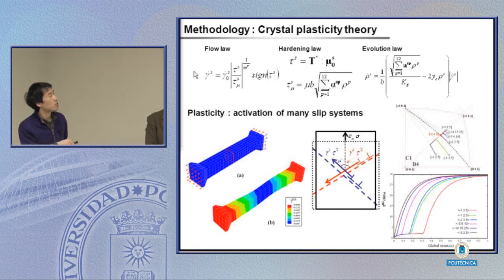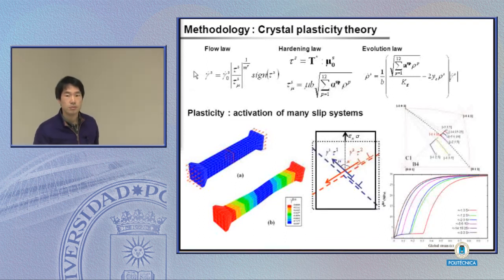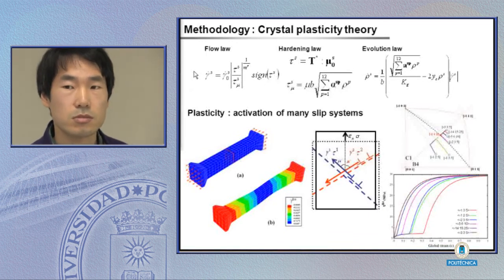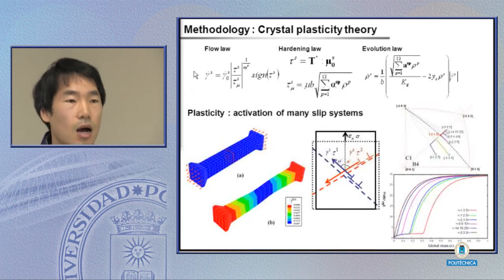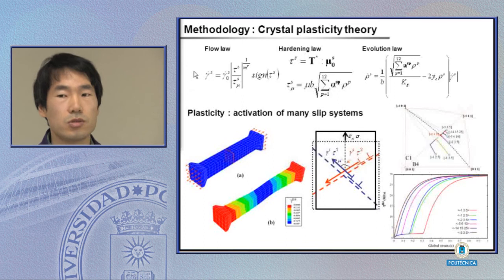The resolved shear stress comes from the elastic stress field, and the only difference is that the critical resolved shear stress comes from the dislocation density and the interaction of the slip systems. And the dislocation density evolves by these Kocks-Mecking evolution laws. There is one density of dislocation for each of the 12 systems? Yes. Different variables? Yeah. And you consider only one density independent of edge or screw dislocations? You have a unique density? Unique density. There's no distinction between edge and screw.